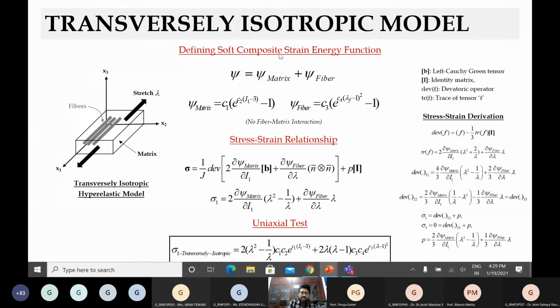So this uses the strain energy contribution of both the matrix and the fibers, and goes through a bunch of refinement steps. And then there is a final stress versus stretch equation and a bunch of constants. So all the hyperelastic models, and this is under uniaxial test only. If there is a biaxial test condition, it would be different. We usually choose to do uniaxial test because it gets fairly complex to characterize something when it's in biaxial mode.